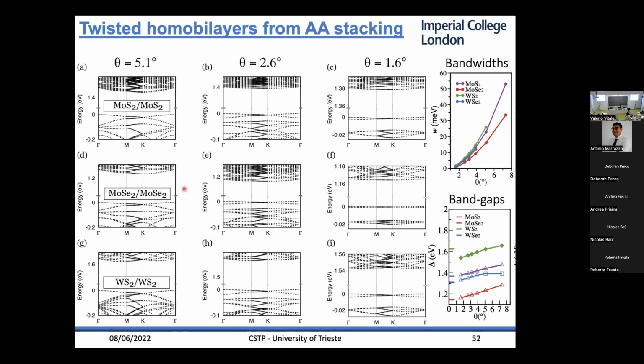Right, so this is just an overview of what happens if you twist the angle. As I said, you start with these two bands that touch at K, and that gives a linear dispersion. Then they become flatter and flatter. At 1.6 degrees, which contains up to 10,000 atoms, you have these very flat bands, particularly for molybdenum diselenide. And for these systems, at 1.6 degrees, you wouldn't be able to do any DFT calculations.